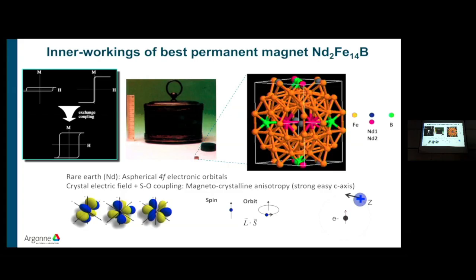And little we knew 20 years ago when this work was done that permanent magnets would become such a large commodity and be central to the trade war between the US and China. It looks like they are as valuable as the most advanced NVIDIA chips. So to get a good permanent magnet, you want the best of these two worlds. You want very large magnetization and you want very high coercivity so that the hysteresis loop is square, a big square, and tall. So the magnetic energy that is stored in this magnet is the area in these hysteresis loops.